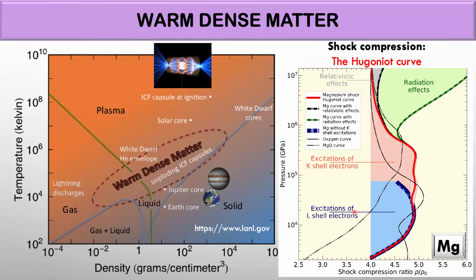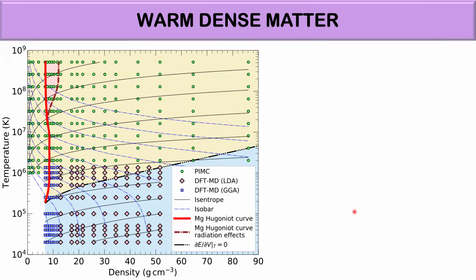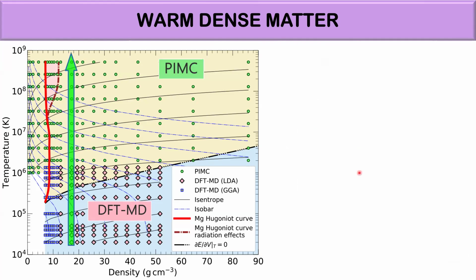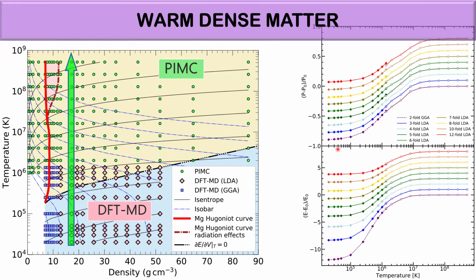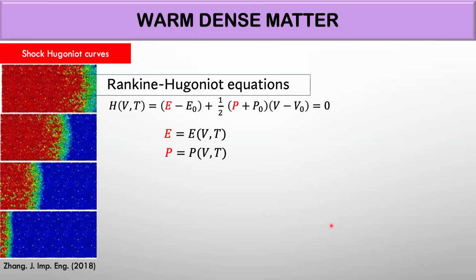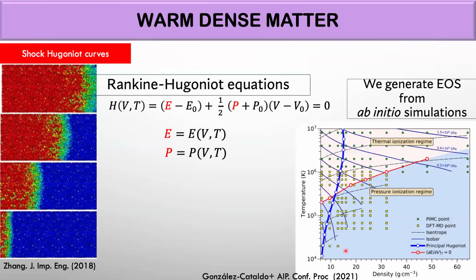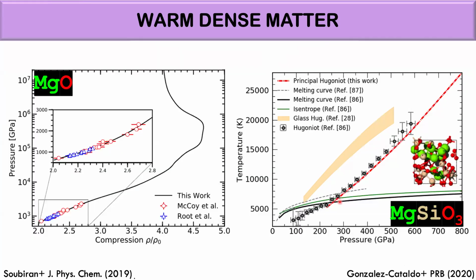We can reproduce these shocks with our simulations, where we basically build a gigantic equation of state, exploring many densities and temperatures, and monitor the dependence of the pressure and energy of a given material as a function of temperature, and see how it changes from a few thousand Kelvin up to a billion Kelvin. We build a consistent equation of state that is important to report properties and build the Rankine-Hugoniot equations. With these, we build this shock curve that I showed you earlier, which characterizes the locus of points of shock conditions in an experiment. And we have been successful in replicating experiments with this technique. You can see here our black line for MgO matches really nicely with shock experiments of magnesium oxide. The same for MgSiO3, where we have pretty good agreement with the experiments, showing you again the predictive power of our simulations.